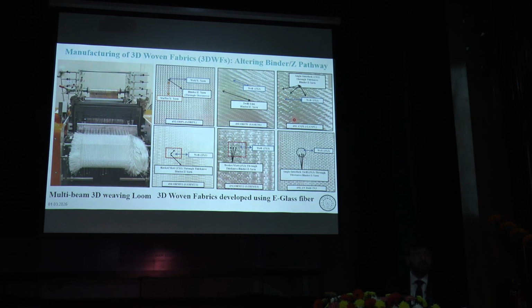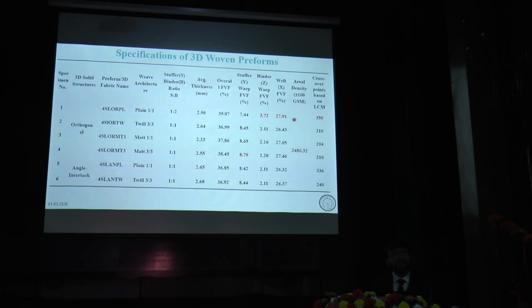We manufactured using 100% E-glass, 600 Tex reinforcement, and developed these 3D woven structures. These are the specifications. We tried to keep the grams per square meter, the areal density of these structures, very close to each other, so there's no manipulation in fiber volume fraction. But due to the nature of the weave architectures and the binder float pathway, changes in crossover points and small changes in stuffer warp and binder warp fiber volume fraction played a significant role - that's what I want to prove here.